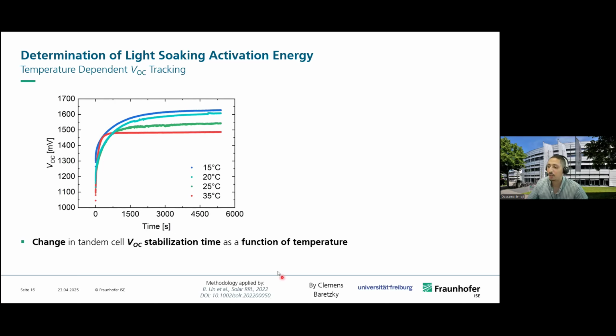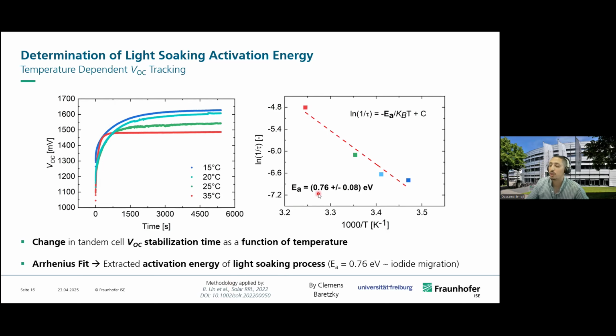Now, by applying the same methodology by Lin et al., where we would use an Arrhenius fit, we could get an activation energy for this light soaking process, which was found to be 0.76 electron volt. And by comparing this to the literature, we found that it was actually in the range of that of iodide migration.